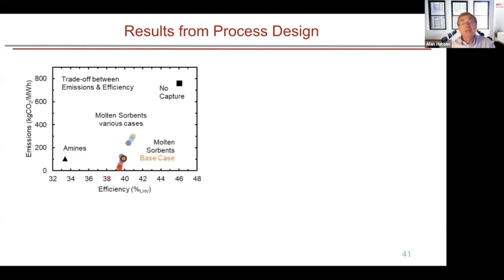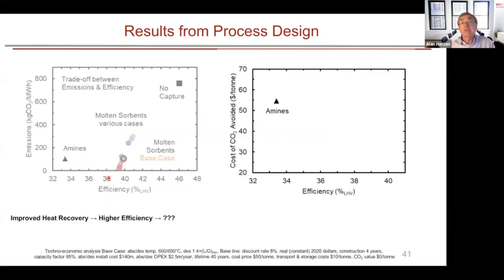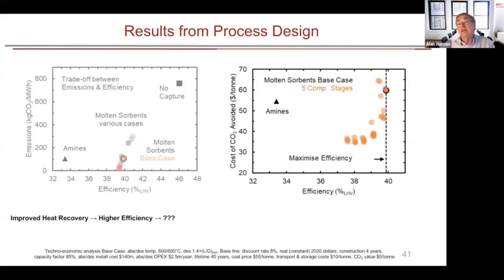And if you look at this as being the base case here, we can then do an analysis around that base case. And the question is, how does this compare in terms of costs? This is the cost of CO2 avoided using traditional amine, on the order of about $50–$55 per ton, and efficiency again of about 34% in this particular case. Our base case, as we pointed out before, was close to 40% efficiency, and the costs are somewhat higher in terms of the CO2 avoided in this case. So by doing an analysis of a number of different combinations, we end up with this type of curve that's shown here, relative to the base case. And the important part is that we have now been able to minimize the cost at some loss in overall efficiency, but not a really huge loss in overall efficiency. And it looks like this could be a very viable approach for us to adopt.